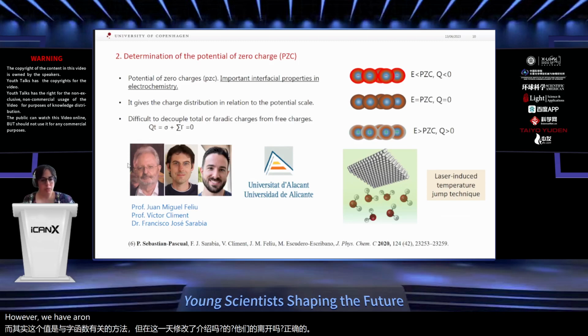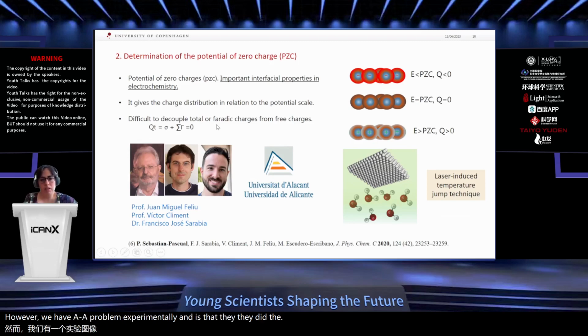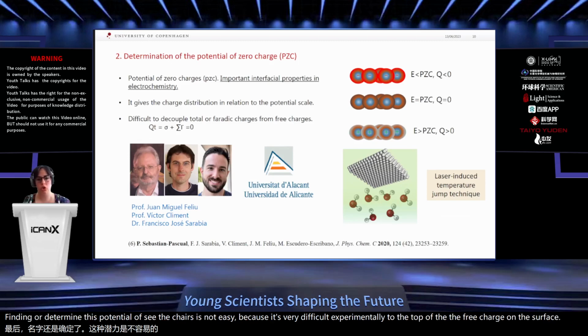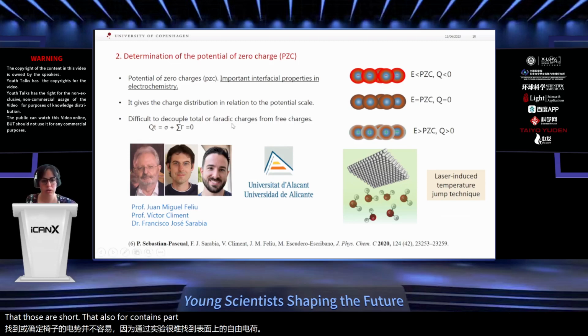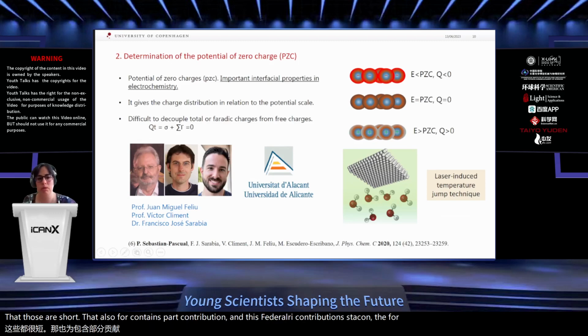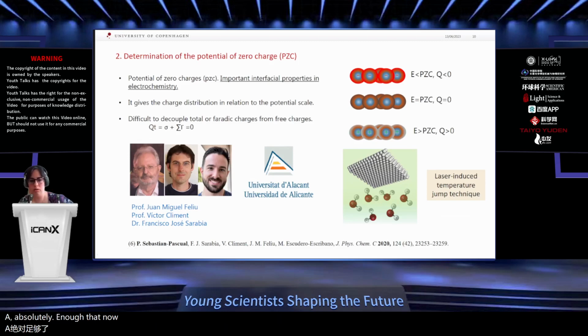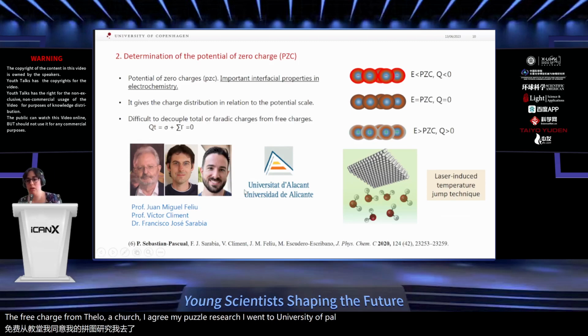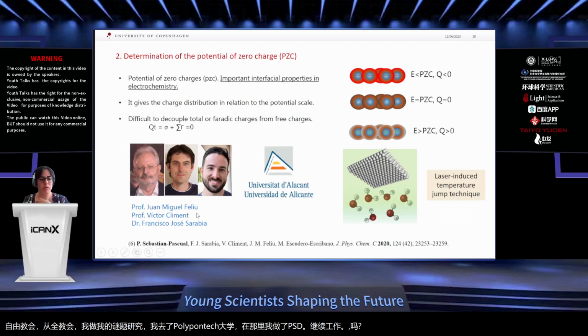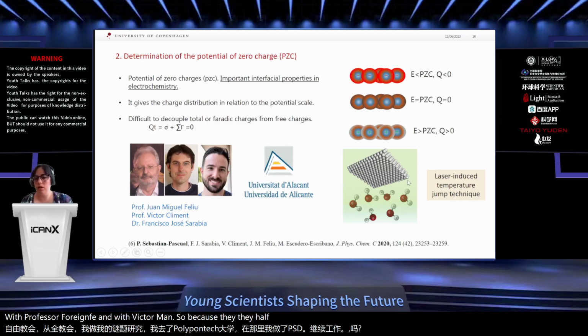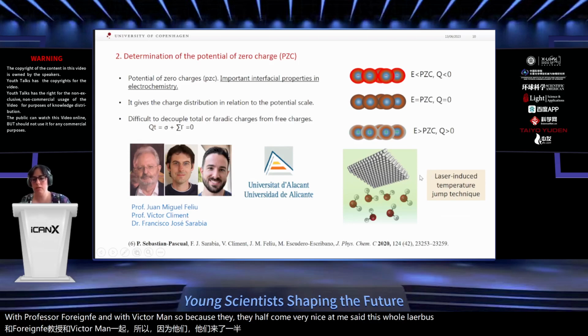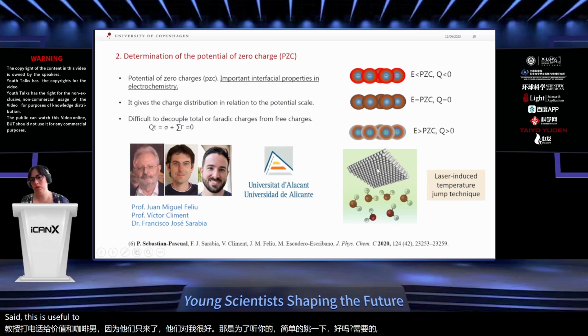However, we have a problem experimentally, and that is that determining this potential of zero charge is not easy, because it's very difficult experimentally to decouple the free charge on the surface from the total charge, which also contains Faradaic contributions. These Faradaic contributions can come, for example, from the specific adsorption of anions, which contribute with charge. So in order to decouple the free charge from the total charge, during my postdoc research, I went to the University of Alicante, where I did my PhD, to work again with Professor Juan Feliu and Victor Climent, because they have in Alicante a very nice technique called the laser-induced temperature jump technique, which is used to estimate this potential of zero charge.